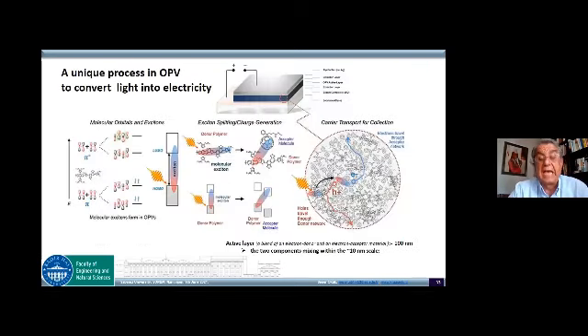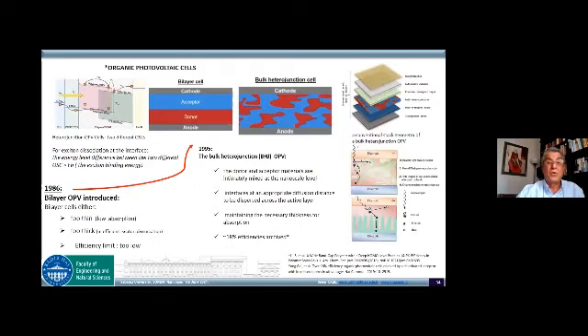But the difference is that everything happens in a 100 nanometer active area. In those cells, the active area is only 100 nanometers. And all the components, the donor polymer and the acceptor molecules, are entangled within 10 nanometers. Everything is at nanoscale. So the technology is nanotechnology. When you look at the early ones, there were bilayer OPVs, but there were problems with that. The bilayer was too thin for good absorption and too thick for efficient exciton dissociation. Then the efficiency limit was too low.